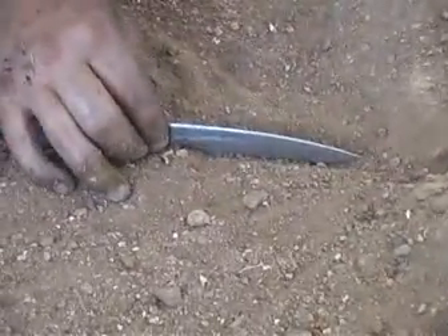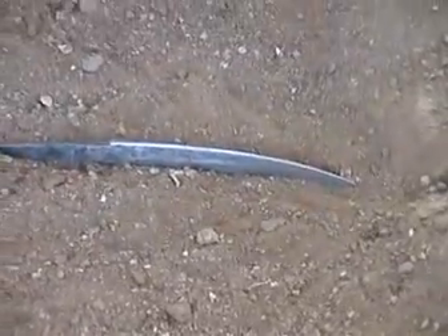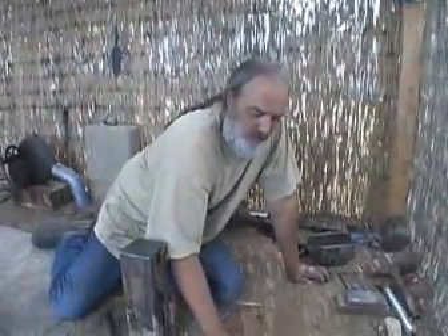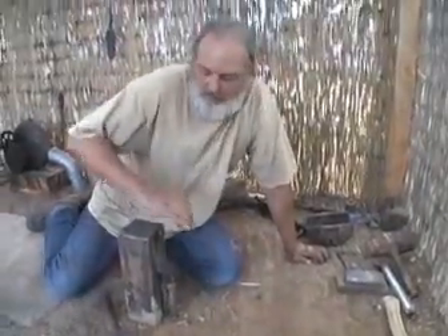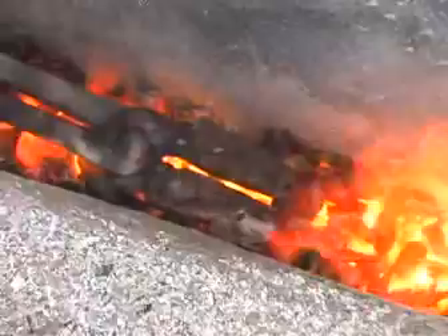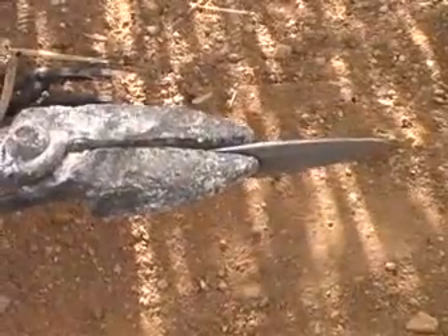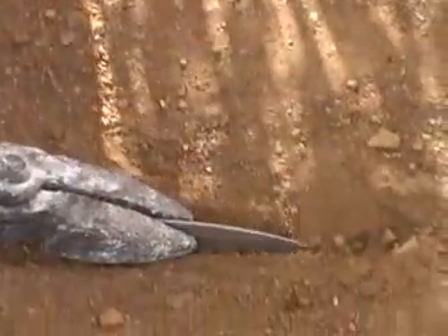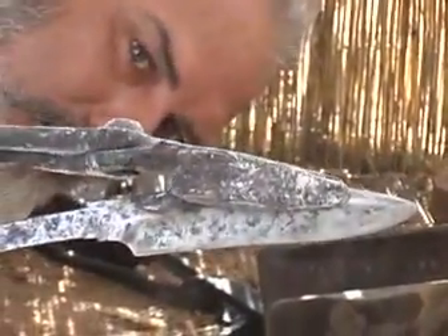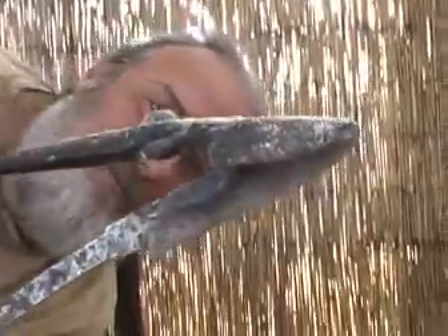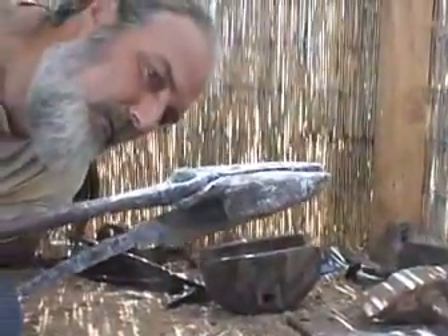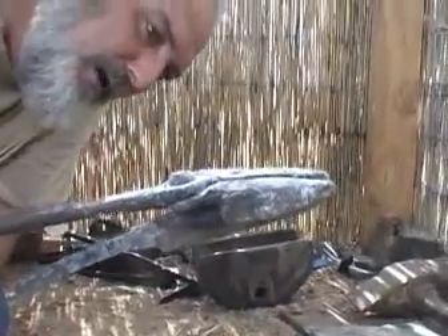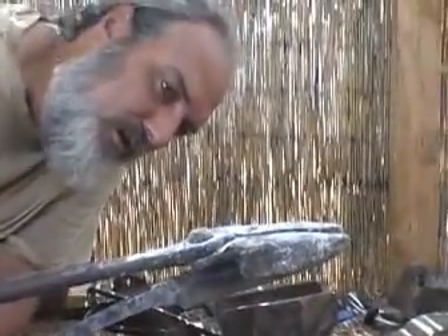And I'll leave it in the dirt when it gets too hot in a spot to suck the heat out of it so it won't get too soft. So now all I have to do is heat up the tongs, and then I'll grab the back. That thing's so thick it takes a while to heat up. You can barely see a straw color starting to come down it. You can see the back has turned a little blue. Works good. So I'm getting a blue in the back, and it's traveling down to like a light straw to maybe a